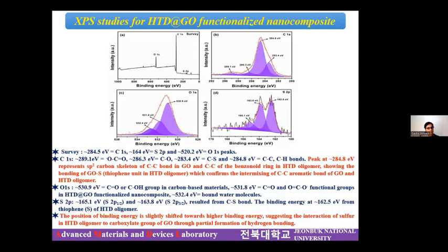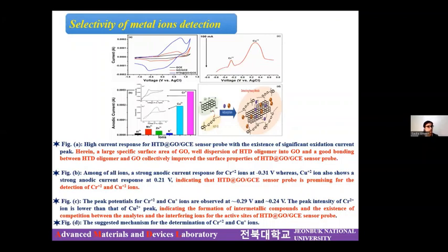Then these are some of the experiments which we have performed just to further show the characterization or to make sure of the interaction between the two moieties. And this is the heart of the work, that is the sensing performance. For this, we have taken the glassy carbon electrode and we wanted to see the effect of our synthesized catalyst for the sensor. So first we performed the catalytic activity without depositing any material over the surface of the electrode. Then we incorporated just graphene oxide, and finally we deposited our synthesized nanocomposite material over the surface of the glassy carbon electrode.